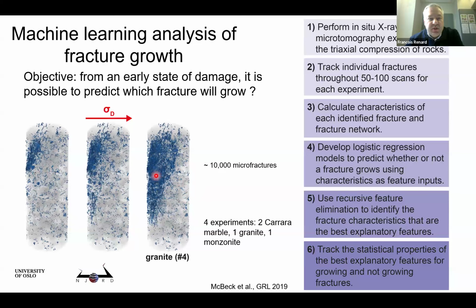What we want to do in the system is predict for each fracture, each of these blue objects, what is controlling their growth. Why does a fracture grow? What is the parameter? So we perform a series of experiments. We have between 50 to 100 of these 3D scans as the sample approaches failure. Then one of the students, Nilima, wrote a code that tracked each of these blue fractures and how each was growing when the sample was loading. Some fractures will grow, but if a fracture grows, a nearby fracture could close.